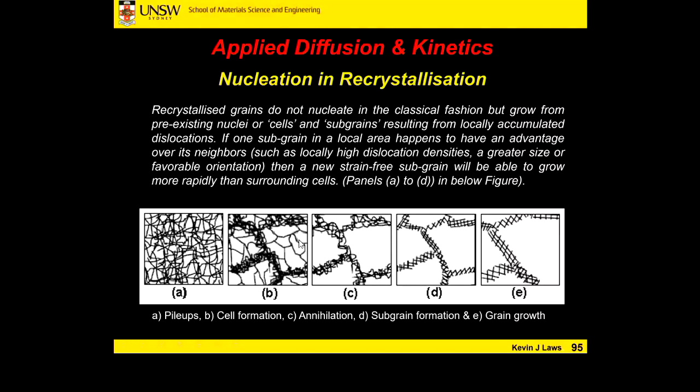These dislocations continue to move to the walls of these cells, and we start having an individual region encompassed by these dislocations. They line themselves up more properly over time, forming cell walls, which are essentially the nucleus or nucleation site for our new grains. These dislocations can then move away and become grain boundaries. The material in here can rotate compared to the parent grain and create essentially a new grain.